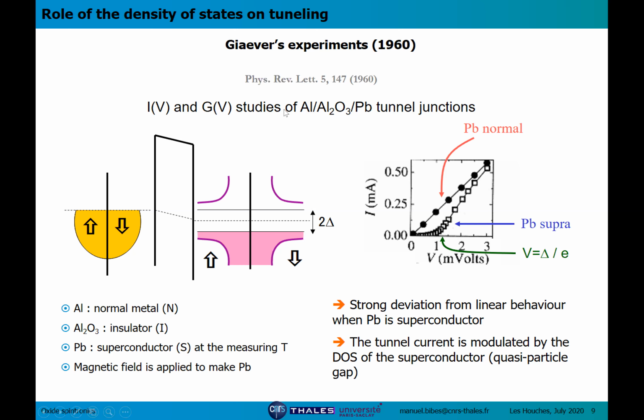Giaever studied tunnel junctions in which the tunnel barrier was again aluminum oxide, but the electrodes were aluminum and lead. And then he worked in two regimes. One regime where both metals are in the normal state, and another regime where the aluminum remains in the normal state, but the lead becomes superconducting. So when lead becomes superconducting, a gap opens around the Fermi level in the density of states of lead, okay?